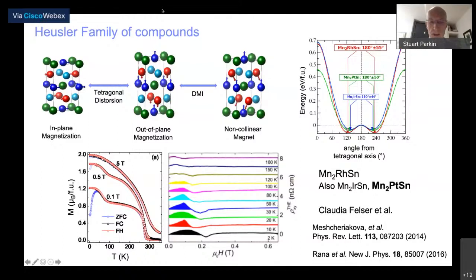And in particular, I first want to briefly discuss some compounds which are called Heusler compounds. Now, Heusler compounds are a very large family of cubic materials, some of which are magnetic, some of which are non-magnetic. And some of the magnetic Heuslers have a distorted structure. They're tetragonal, and the magnetization can be out of plane. There's an out of plane magnetic moment direction from the tetragonal distortion. These are also ferrimagnetic, and not ferro, they're ferrimagnetic systems. So a typical Heusler I'm going to discuss is, for example, manganese 2 platinum tin.